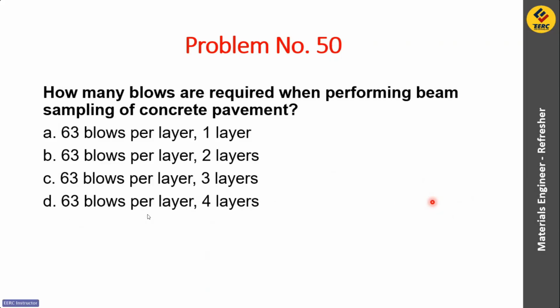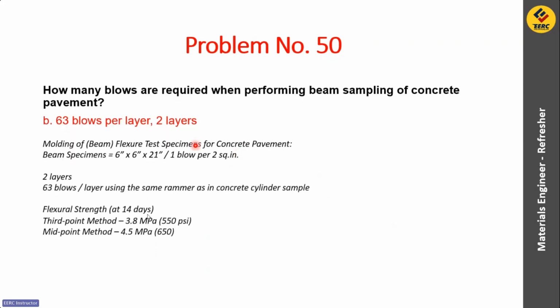Okay, next number 50. How many blows are required when performing beam sampling of concrete pavement? So answer natin dito is 2 layers, then 63 blows per layer, letter B. Yan, for molding of beam, a flexure test specimen for concrete pavement, beam specimens is 6 by 6 by 21, wherein 1 blow per square inch yung requirement natin for that. Then for the number of blows, we have 63 blows per layer using the same rammer as in concrete cylinder sample. So a total of 2 layers for this. Please take note the flexural strength at 14 days for third point method is 3.8 megapascals or 550 psi, and for midpoint method 4.5 megapascals or 650 psi.